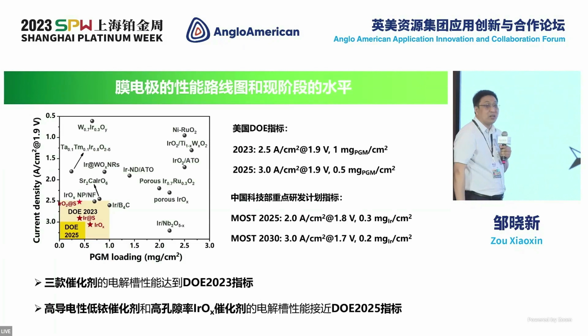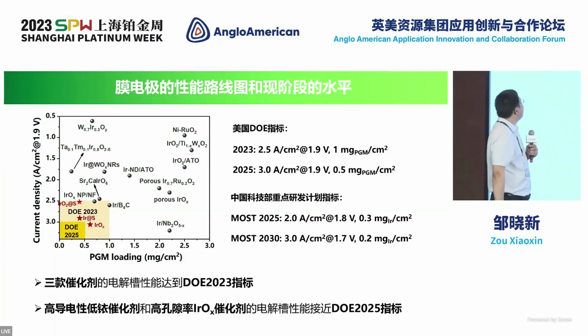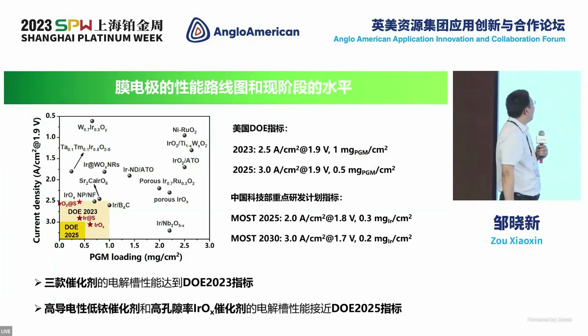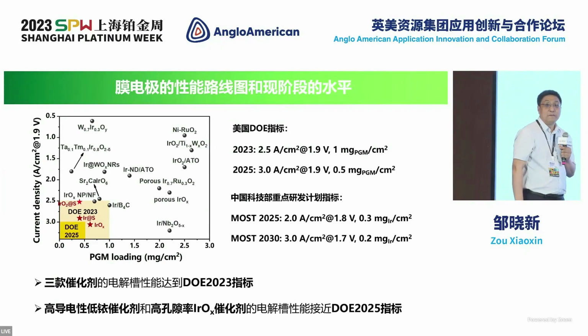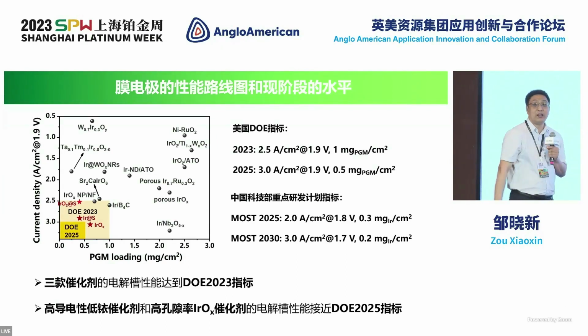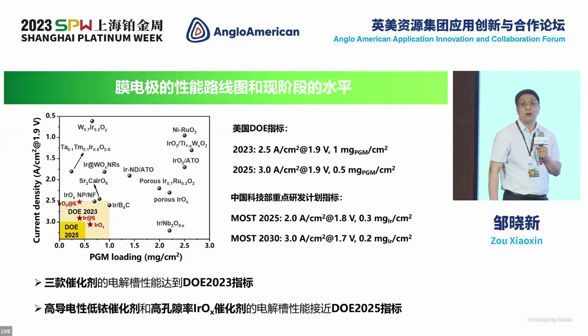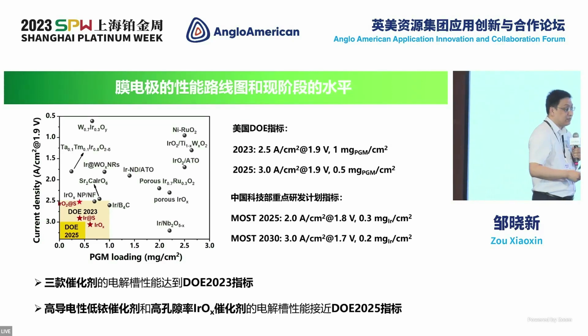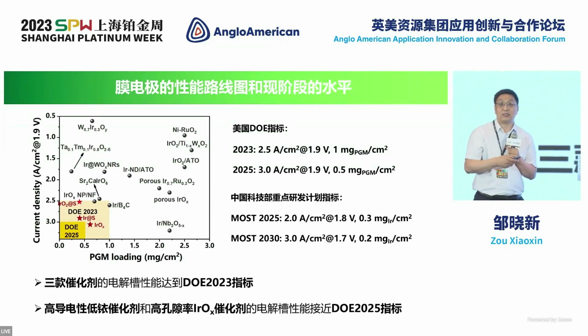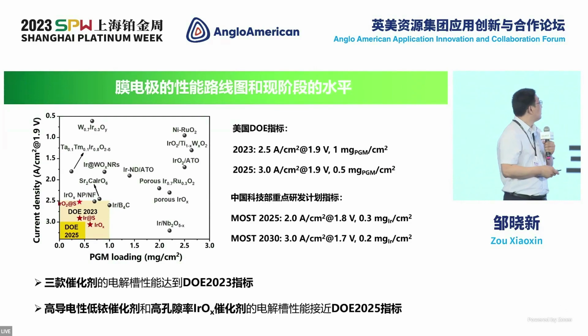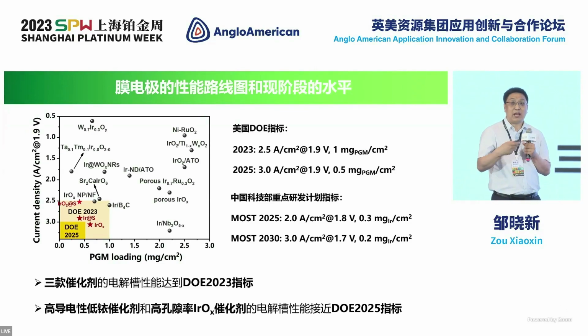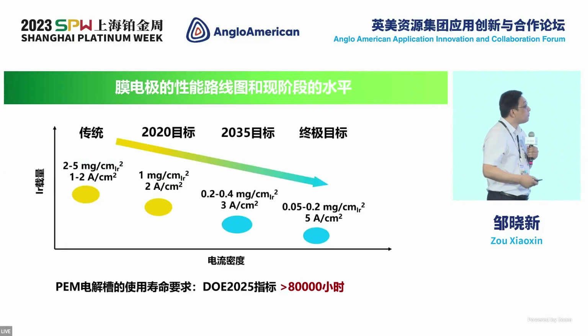And in 2023, the loading is 1 milligram per square centimeter. As for current, it should be 2.5 amp per square centimeter. And there are only a few players who are capable of attaining this goal. We are very fortunate that 3 of our catalysts are able to fall into the category, and potentially we have 2 more to reach the target for 2025.